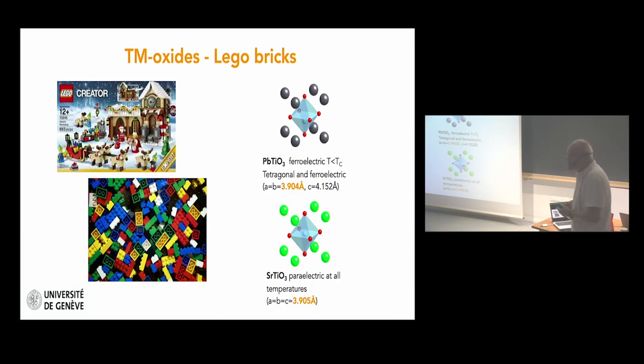Additionally, many of these materials have rather similar lattice parameters. You see an example with lead titanate, which is a rather famous ferroelectric material. You see that in plane, the lattice parameter is 3.904 angstrom. You compare to strontium titanate, which is paraelectric, 3.905. So these unit cells are rather similar, and so it's a little bit like Lego bricks, and it allows us to realize rather perfect structures today using different techniques.